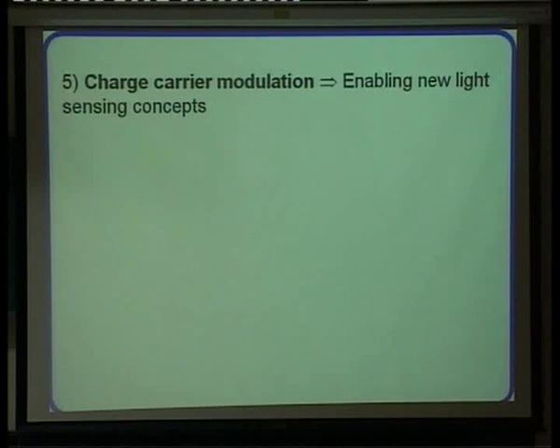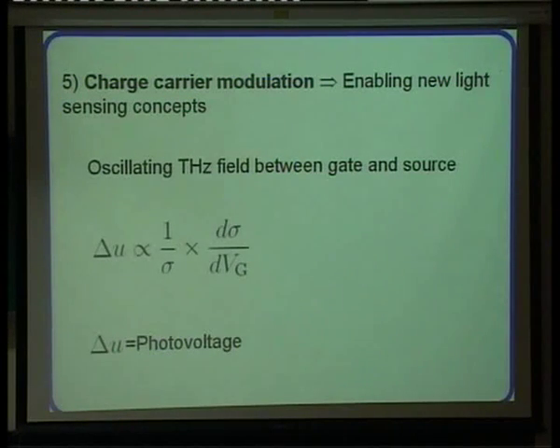And to answer the question of Arindam before, what happens if we go to the terahertz? We have the doping. Doping is impossible to get rid of at that stage, so Pauli blocking will always block the interaction of light. You will not have a generation of electron-hole pairs, so in principle, graphene will not be useful in the terahertz range. However, if you have an oscillating terahertz field between gate and source, you can generate a photovoltage based on this simple relationship. It is the old relationship by Dyakonov and many other people. It's a well-known effect. You can essentially interact with the plasmon in the graphene, and that will generate a modulation of the charge of the channel, and that gives you the photovoltage.